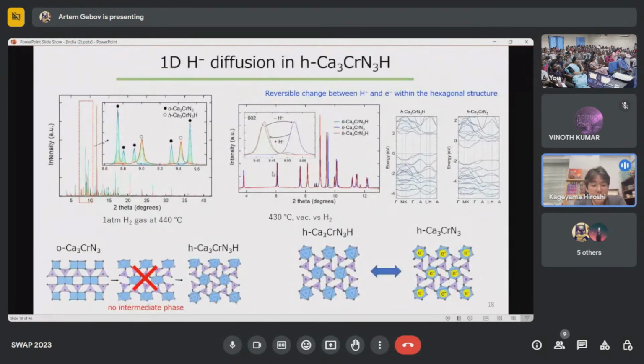Then we did some further analysis and experiments and found that the phase transformation with the hydrogen or hydride insertion occurs in a biphasic manner. So actually, we didn't find any intermediate phases. By measuring the X-ray diffraction in situ, we found that only the ratio between the orthorhombic phase and the hexagonal phase changes.